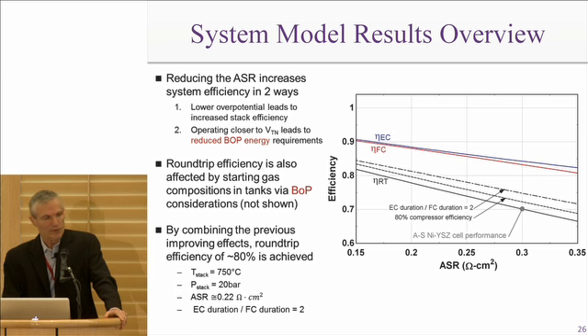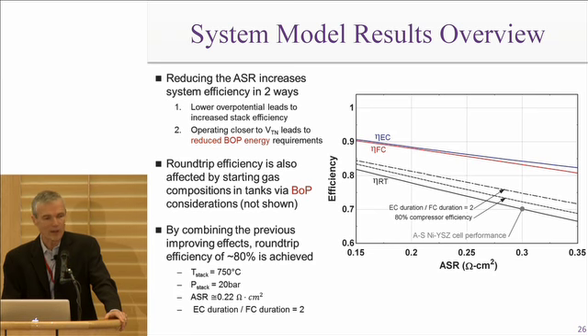Okay? And what we can see here is that if we get down to this value of about 0.2 ohm cm squared that we were talking about, actually in a realistic system, and these different curves here are showing different assumptions, which I don't have time to get into, but basically we are getting, in a real system with all the losses in it, compressors and heat exchangers and whatnot, we can still contemplate the idea of getting 80% round trip efficiency on these devices.